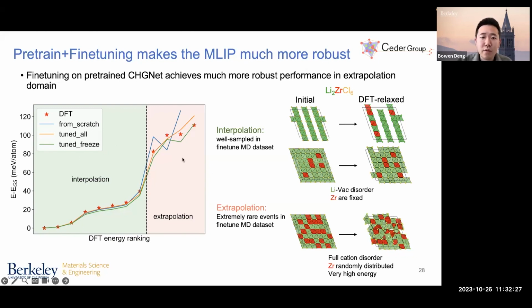However, when the model is extrapolated to these fully disordered structures, where we randomly distributed the zirconium sites, such zirconium site orderings are actually extremely rare events to be sampled within this fine-tuning dataset. As you can see, these star points in DFT tell you that they have very high energies compared to all of these green points. That's an indication that you really cannot sample these events in the AIMD. And in this region, the pre-training plus fine-tuning strategy achieves a much better and much more robust result than just training CHGNet from scratch. This result highlights the importance of the generalization effect from a comprehensive pre-trained dataset and shows the advantage of foundation models like CHGNet, which enable a faster and more reliable fine-tuning for downstream tasks.